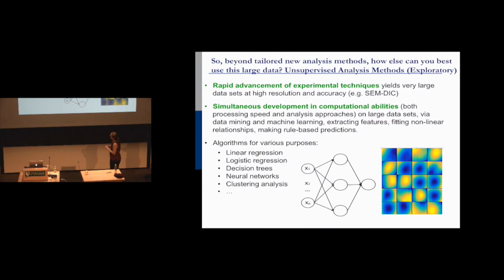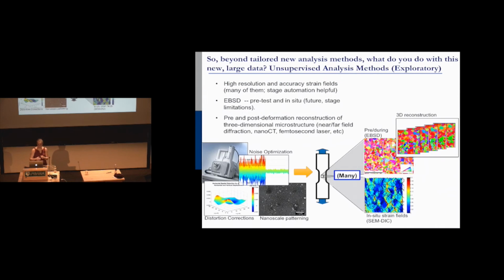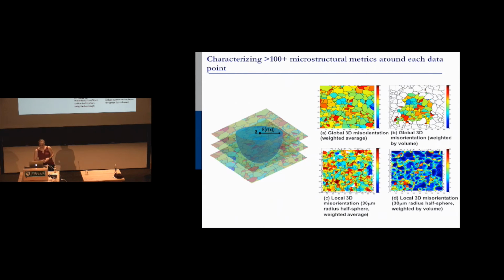The way that we're working on it, and this is super new, is we take all our data. We take the methodology that we developed with noise optimization, distortion corrections, and nanoscale patterning, and we get all this EBSD data that tells us the microstructure. We can get a 3D reconstruction of what's going on through the specimen, whether by nano-CT or by polishing in EBSD. And then we get many, many of these strain fields, where each one of these dots has an associated damage and the 200, 300 microstructural variables. And then we characterize those variables as follows.